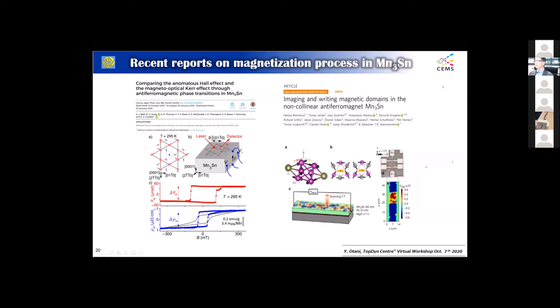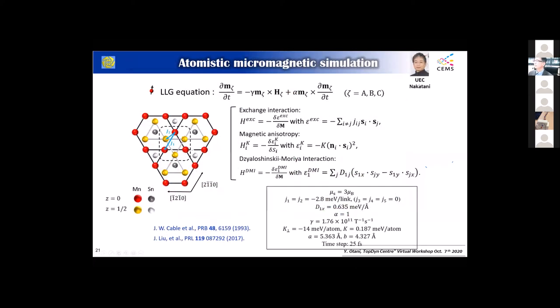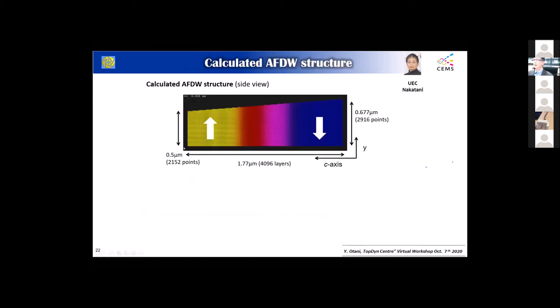What we did was collaborate with Professor Nakatani at the University of Electro-Communications. We started with the LLG equation, taking into account the effective field including exchange, anisotropy, and the Dzyaloshinskii-Moriya interaction. All these interactions are converted to the effective field and the system is minimized. The exchange interaction, DM energy coefficient, damping constant, gyromagnetic factor, anisotropy, and all these basis constants and time steps were used — typical values obtained experimentally. We put the boundary condition with the left-hand side up and the right-hand side down.